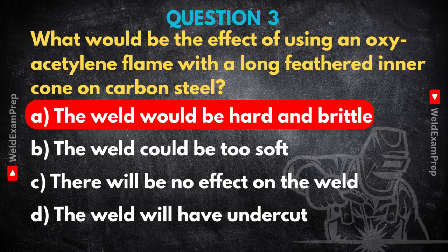And carbon makes steel harder, right? It does, but here it's uncontrolled and excessive. It forms iron carbides, which are very hard but also very brittle compounds, both in the weld metal itself and in the heat-affected zone right next to it. So you end up with a weld that's significantly harder, yes, but it loses its ductility, its ability to stretch or deform, and its toughness, its ability to absorb impacts.